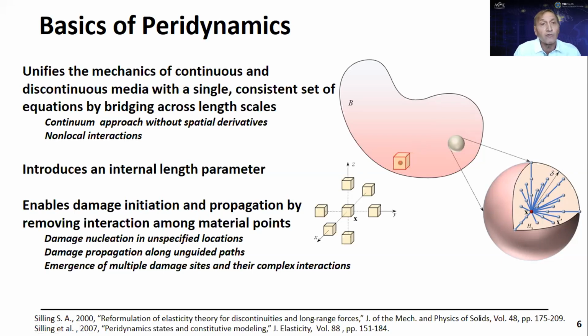So the main robustness of Peridynamics is that it enables damage initiation and propagation by removing interactions among material points. So that way we can nucleate damage in unspecified locations, damage propagation is unguided, and you can have emergence of multiple damage sites and their complex interactions.